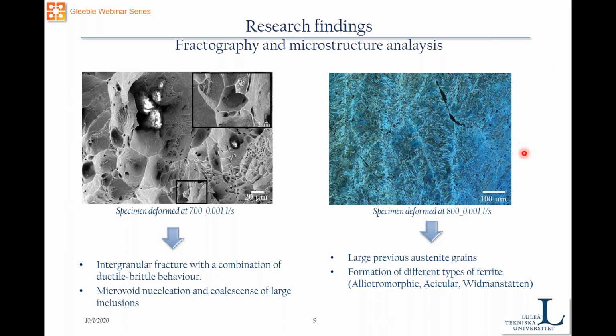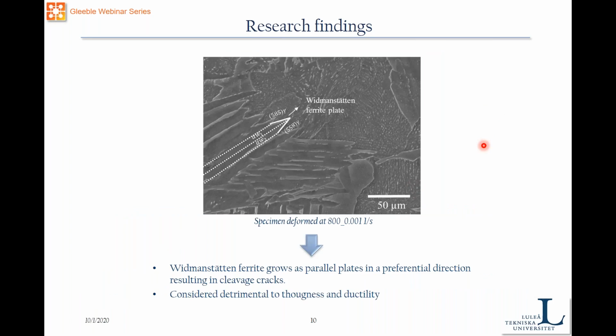On the right side, in the microstructural analysis, we actually saw a combination of different phases. We saw that we normally have a ferritic and pearlitic structure, but within the ferrite structures, we found a combination of allotriomorphic ferrite, acicular ferrite, and Widmanstatten ferrite. Of course, it is quite difficult to see it here, but according to the literature, Widmanstatten ferrite is considered detrimental.